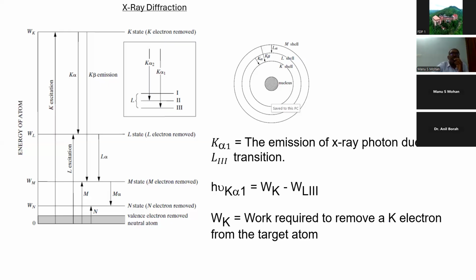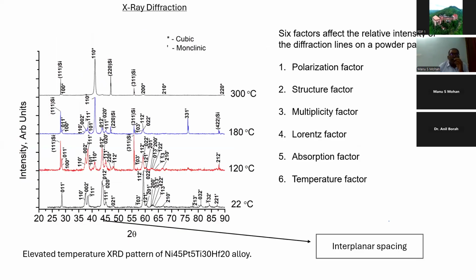So now in the X-ray pattern, when you have K alpha 1 and K alpha 2, you have this issue that K alpha 2 will be very close — it's called a doublet, so it has to be stripped off. So most of you who do X-ray, when the operator gives you the pattern, or when you practically do that, you will definitely be stripping off K2.